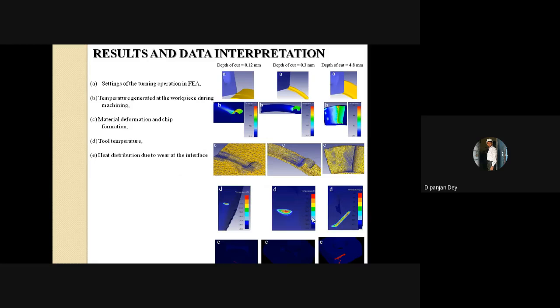These are the settings of the turning operation in finite element analysis. Here you can clearly see the prior settings, the initial conditions, then the temperature generated at the workpiece in these three, and the material deformation also. The mesh clearly shows that the material is being deformed as chip formation is taking place. The tool temperature develops as it proceeds onto the rake surface. The heat distribution due to wear at the interface. This is due to the wear.